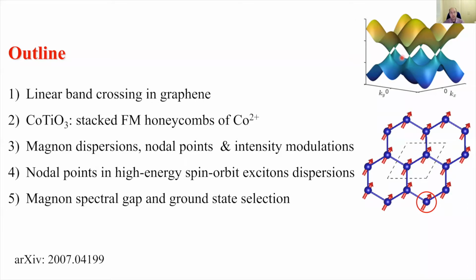And then finally, I'm going to describe some unexpected features we've seen in the experiment. In particular, the spins are ordered in the XY plane, but semi-classically, there's no mechanism to explain why they have a gap. And then we do see a preferential ordering direction and a gap associated with this. And then I'm going to describe possible mechanisms based on going beyond the semi-classical description to understand the origin of the spectral gap.